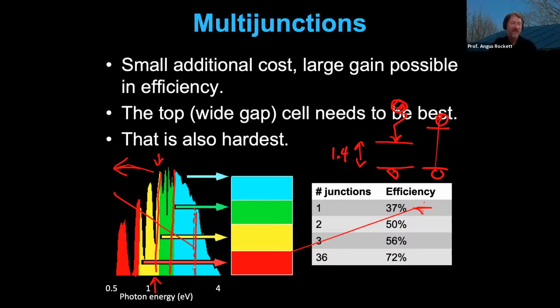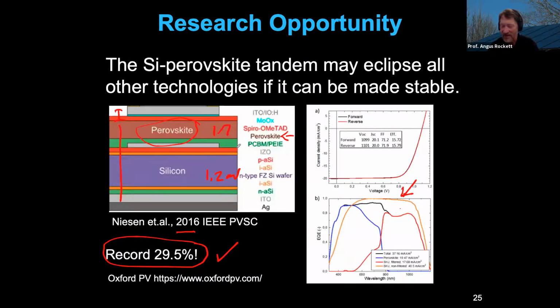You can do it. If you do that, then you have to chop the rest of the spectrum up into lots of little pieces. That's where you get into a 6-junction cell, for example. But now you're getting into a problem. One of the tricky parts that I didn't really talk about is how do you make an electrical connection that's transparent from the bottom of the perovskite to the top of the silicon. In this case, with silicon, it's relatively easy because you say, well, okay, I can make indium zinc oxide or something like that, and that'll make a contact to my PCBM and to my P-type silicon, so I'm good.